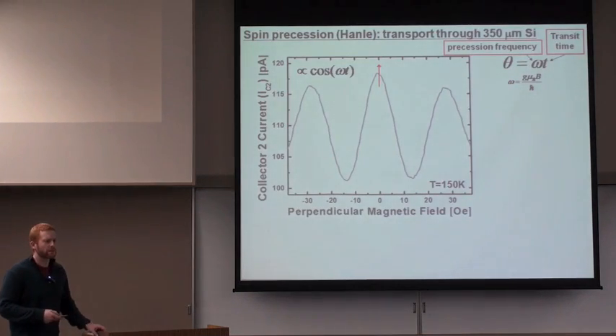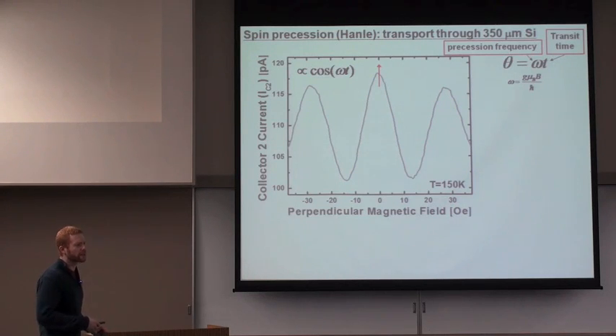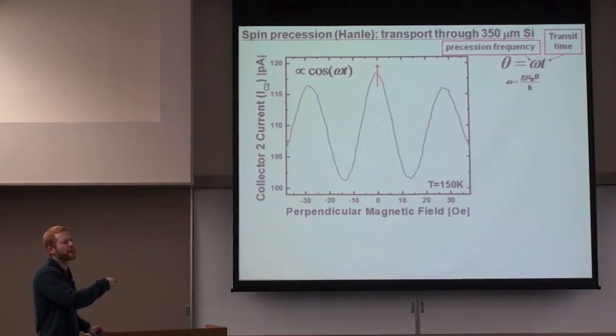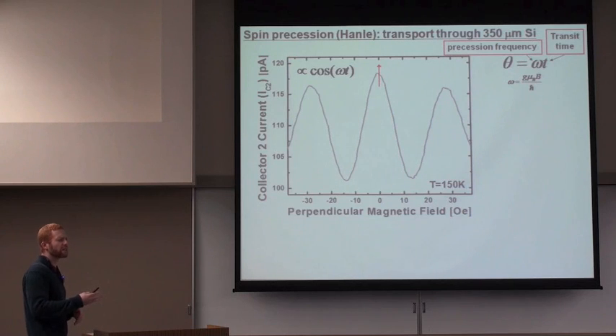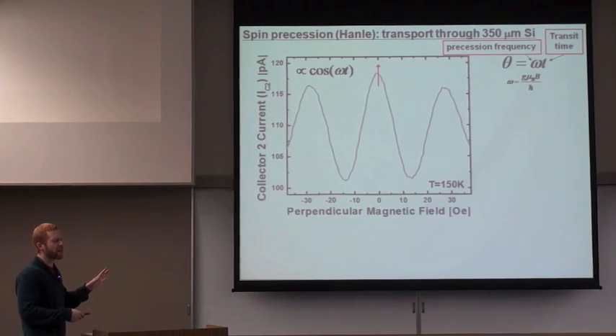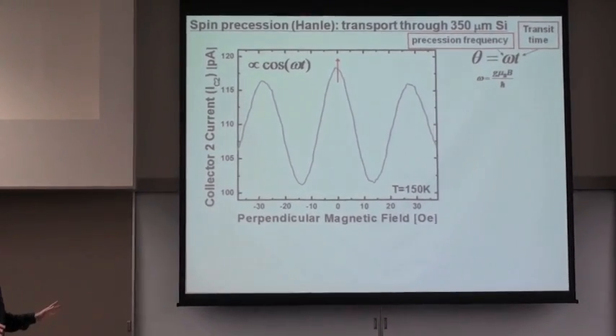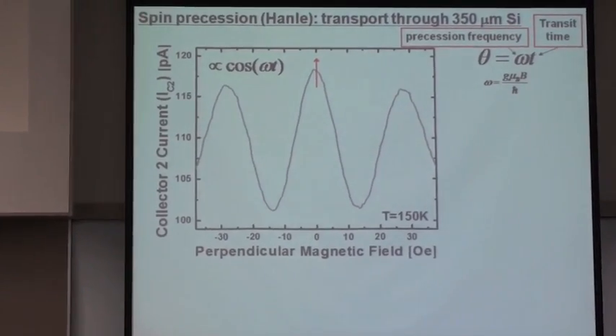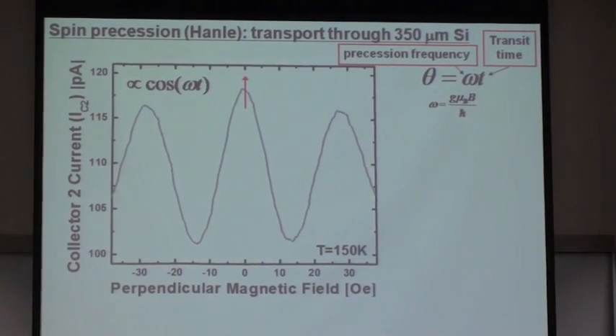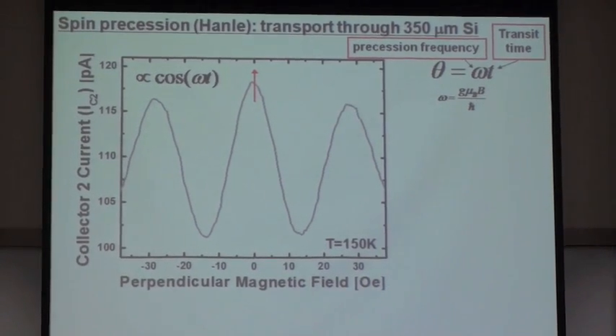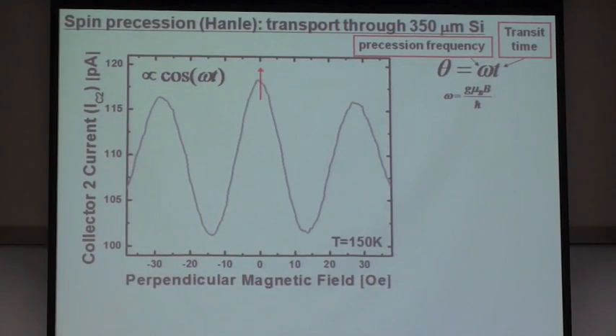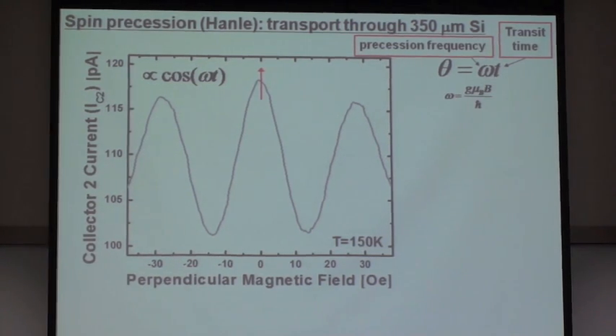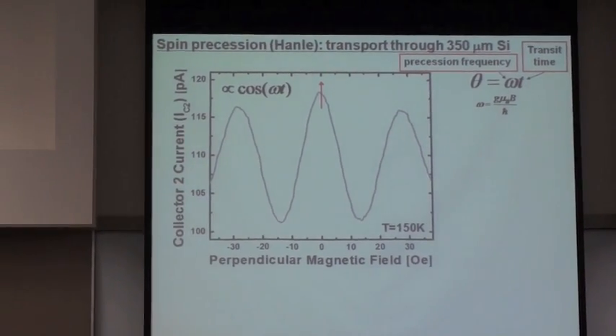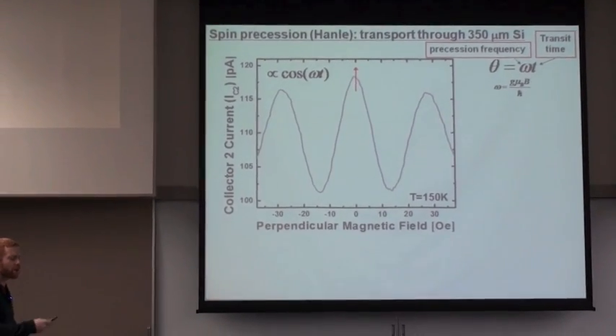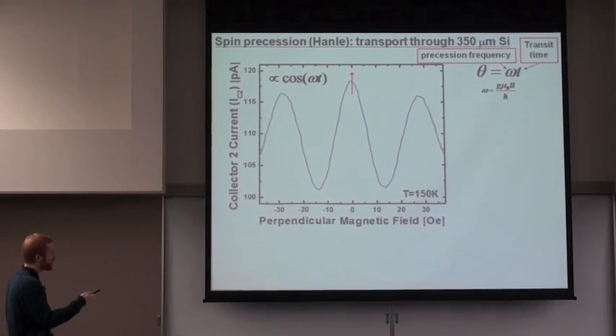So what happens when we do the measurement? This is results on the same device where I showed you the so-called spin valve, where we're just changing the magnetization of the contacts. Here now, the magnetization of the contact is not changing because we're applying a perpendicular magnetic field. We have thin film ferromagnets, which have a very strong shape anisotropy. The magnetization always lies in the plane. Magnetization doesn't change, but the influence of the magnetic field on the spin, independent of the magnetization, causes spin precession and the results I'm going to describe now.